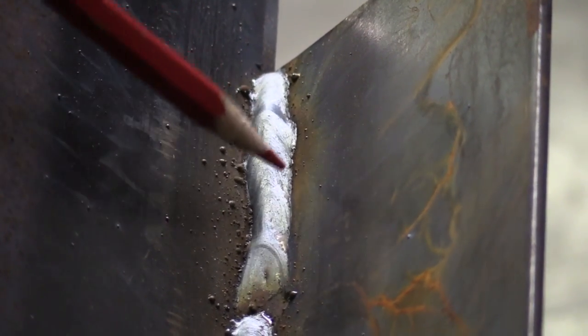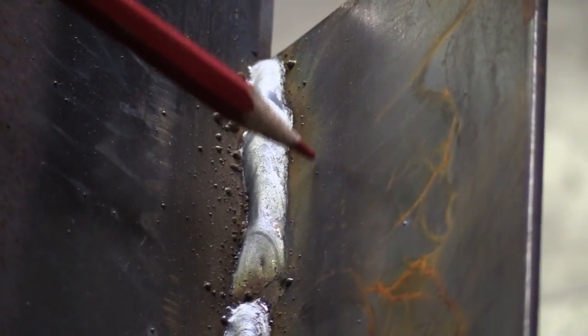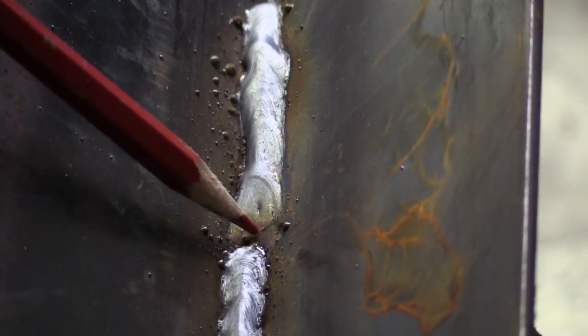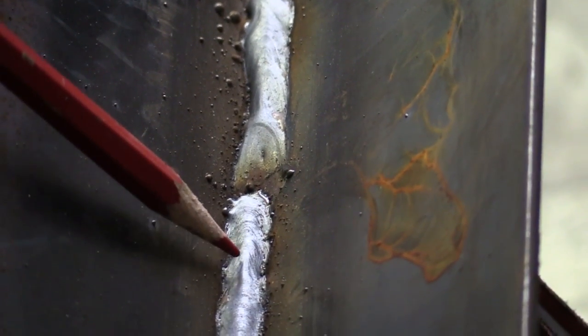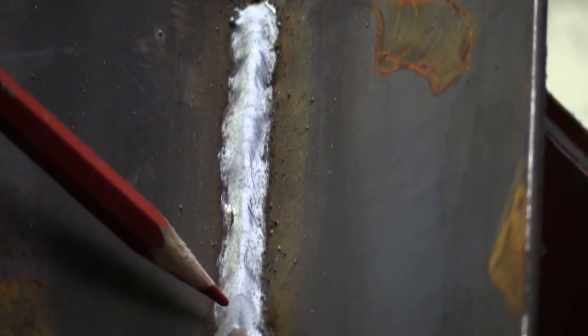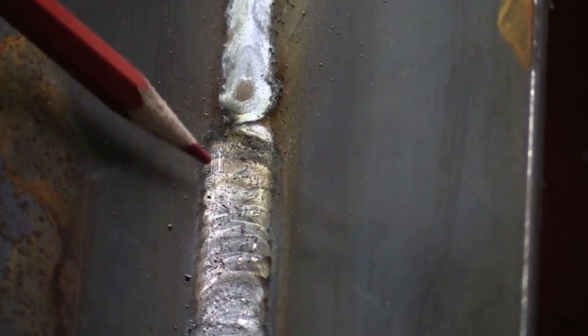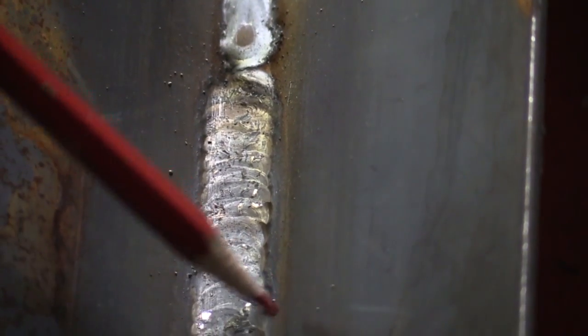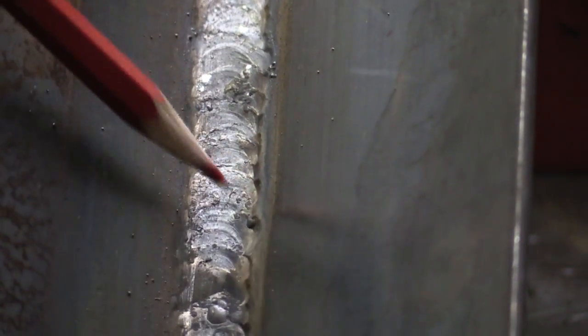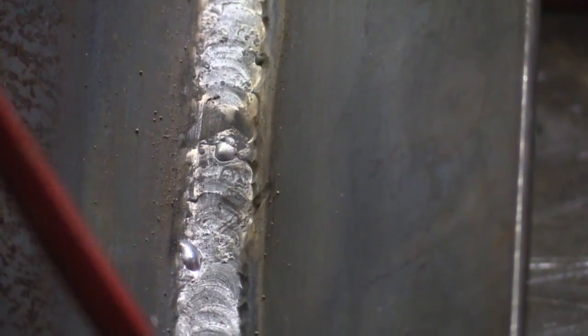Here's the weld that I did not straighten out. Starting at the top of this piece, the weld got over onto this side pretty well but almost missed here. Moving down, you can see where it dropped back into the joint the way it's supposed to be, but too fast, not enough wire, not enough heat. Then down here is where I started with the TIG — just sweep it back and forth, smooth it in a little bit. There's undercut right there where I got a little too high as I swept up, not enough filler, but it helps blend it all in.